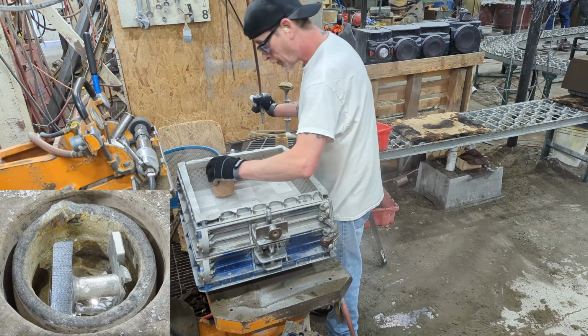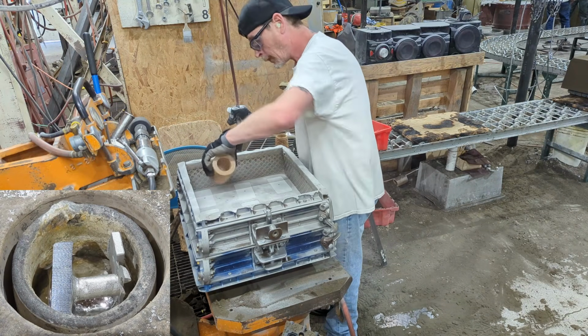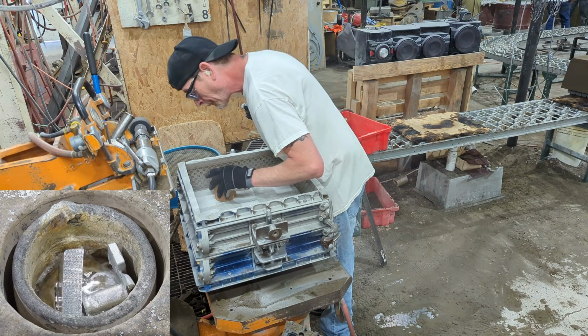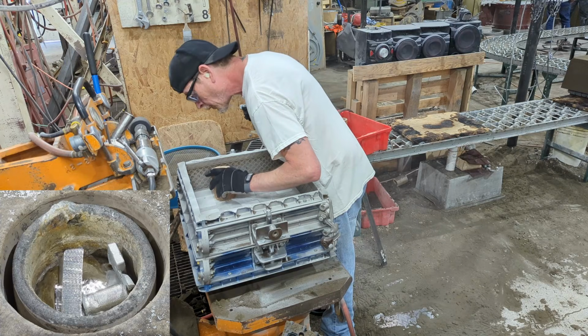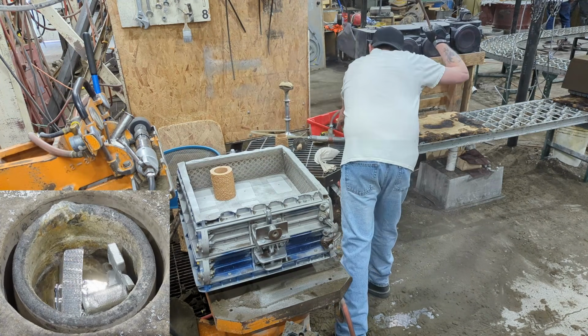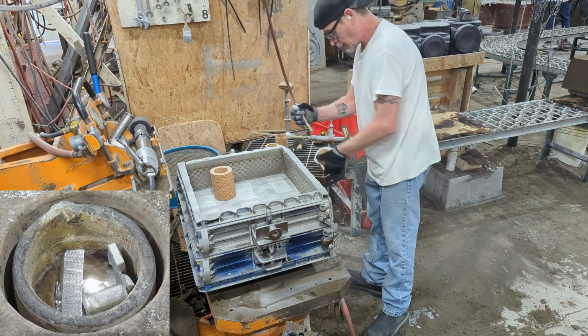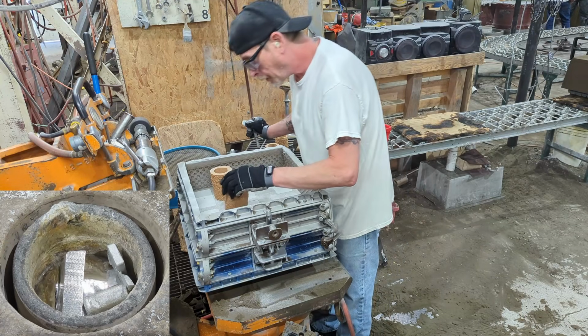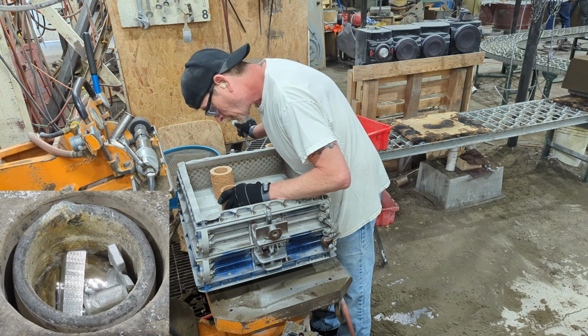Chad then positions thermal risers over the mold. A thermal riser is an insulated cup-shaped sleeve that holds a small reservoir of molten metal above each part. As the casting below cools and shrinks, that liquid metal feeds down to fill any voids, preventing shrink defects in the finished part.